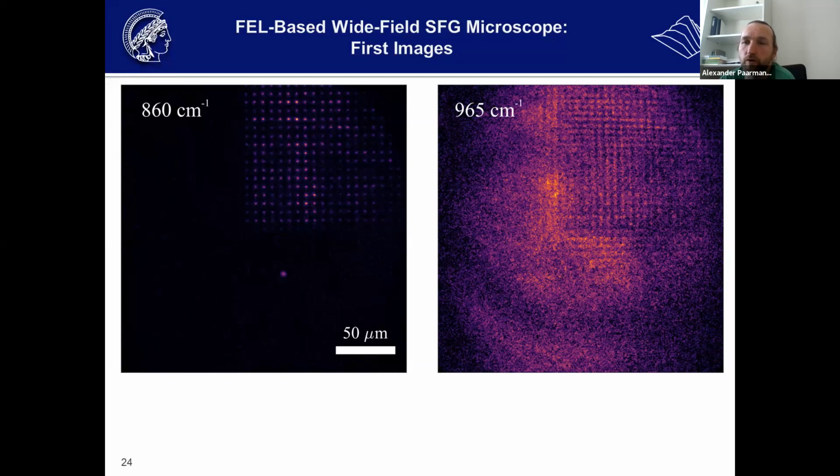And then if you have strain in bulk, you will shift phonon modes. That's known, and in principle, this would be susceptible to. If you would also shift surface phonon resonances with the strain in the bulk, that's non-trivial. I don't know, because that's sort of the dangling bond that's looking out of the surface. To what extent this will see the strain in the bulk, I don't actually know.